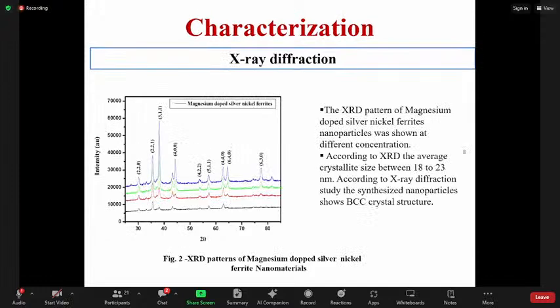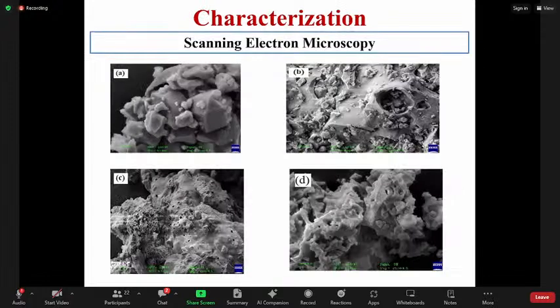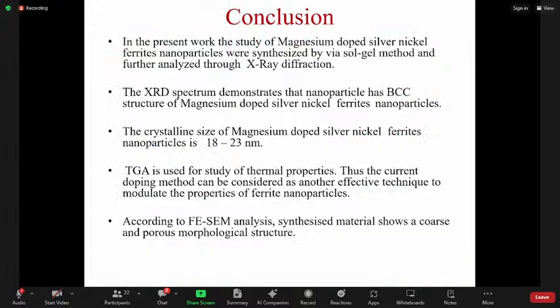After that, the most important characterization is the XRD for the crystalline size and the crystal structure. So this is my XRD pattern of magnesium doped silver nickel ferrite nanoparticles at different concentrations. According to this XRD, I got the average crystalline size between 18 to 23 nanometers. And by the Debye-Scherrer equation, I got the crystal structure, that is body centered cubic structure, BCC. The next characterization is scanning electron microscopy. And I got this porous structure. I got the morphology by this.